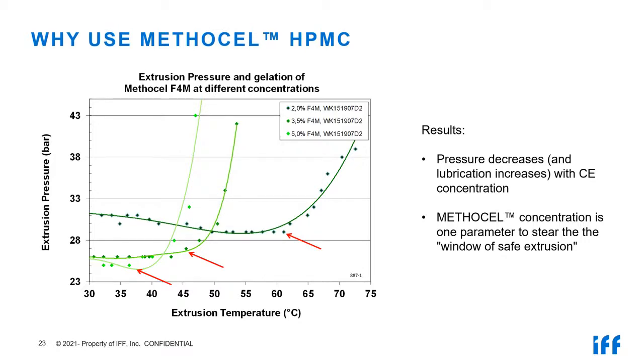First, the line shows a slight decrease. This is a normal effect which you observe in every polymer solution when you heat it up. Normally the viscosity drops. But in this case, you are coming to the gelation temperature close to 60 degrees, and then there is a sharp rise of the extrusion pressure. And why? Because, of course, the cellulose ether flocculates. It's not soluble anymore. If it is not soluble anymore, it cannot contribute to plastification, lubrication, and so on. And that's the reason why the pressure is rising.